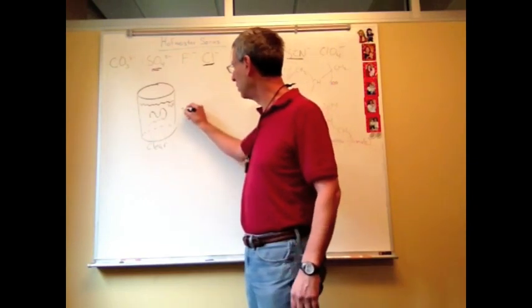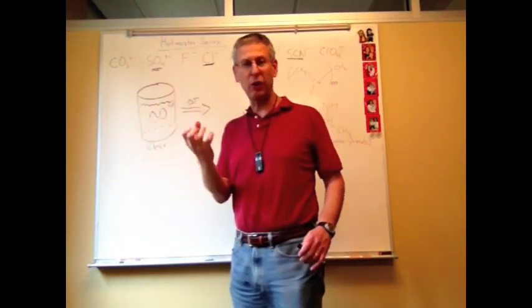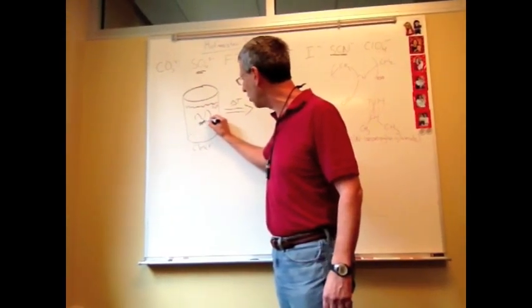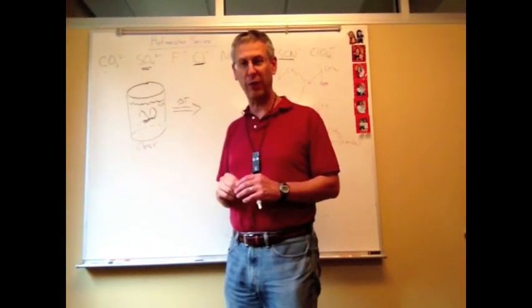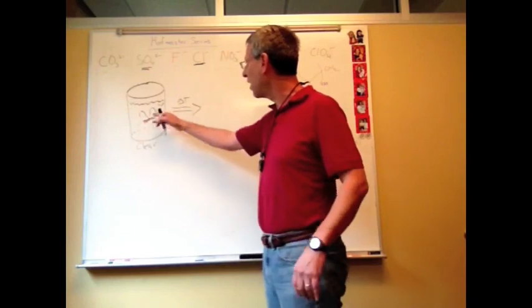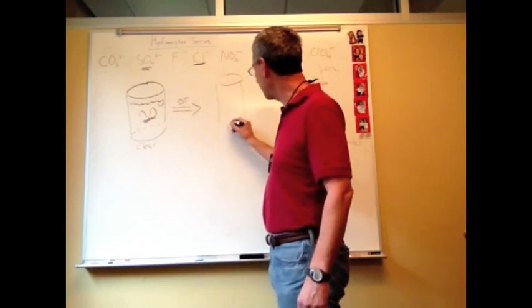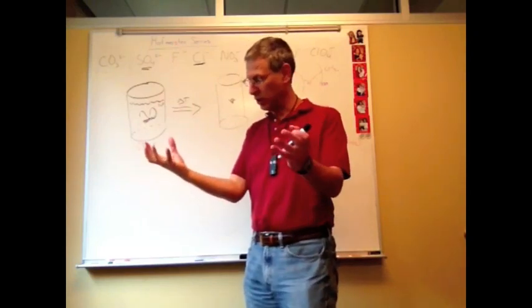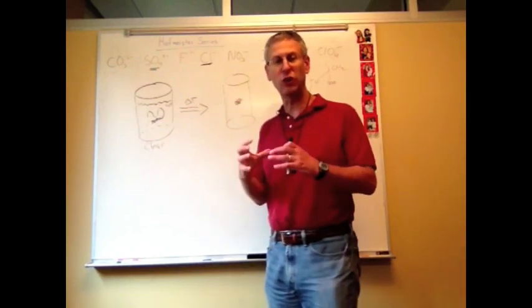If I heat up this solution, these polymer molecules are going to collapse. They're well hydrated in this state, and all the monomers along this polymer chain have specific hydrogen bonds to water. The water molecules surround them very well. When I heat this up, the water desorbs from the surface. This molecule collapses in solution and aggregates with other molecules. This well-hydrated string suddenly collapses into a ball with other polymer chains to form larger aggregates.